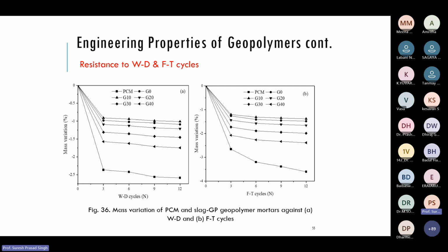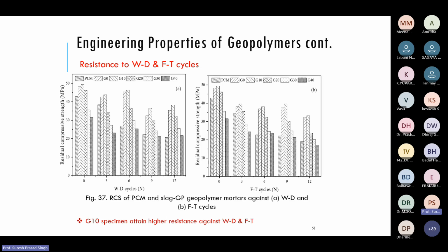And you see that this is for the conventional cement mortar. There is a continuous mass loss with exposure cycles, whether it is wetting drying or freezing thawing. But you see that this one is for geopolymer mortar. After a mass loss of about 1.2%, it gets stabilized. But here it continues for longer cycles of wetting drying and freezing thawing. This is again the resistance to wetting. This is for the residual compressive strength. A similar thing you also observe.